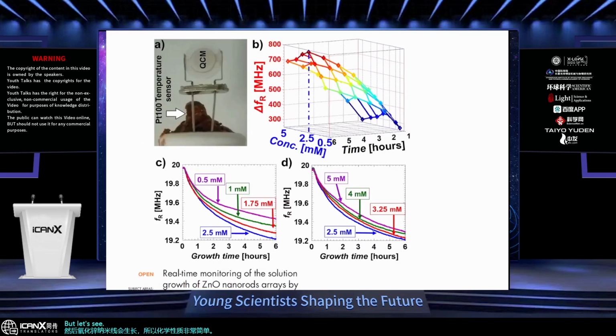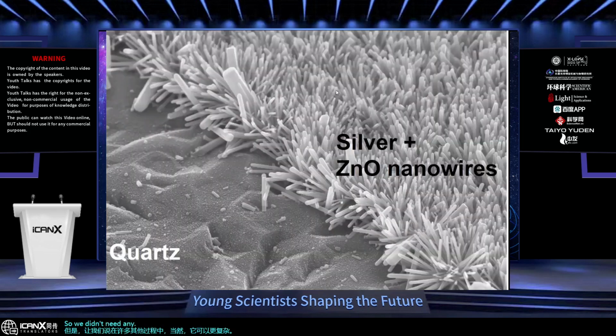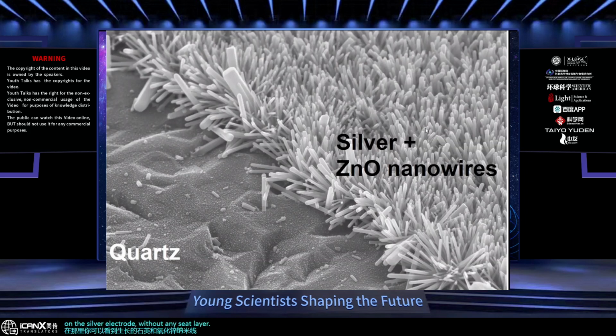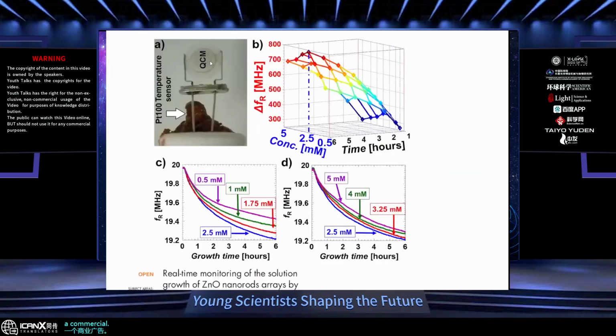But let's say in many other processes, of course, it can be more complex. So we didn't need any seed layer or anything. This is just an SEM photo where you see the quartz and the zinc oxide nanowires that grow on the silver electrode without any seed layer, just wet chemical. So in our case, it was very simple because of this selection. This is actually just a conventional commercial quartz. So we just open the cap and we have the silver electrodes, we place them in the wet chemical solution, and the zinc oxide nanowires grow.